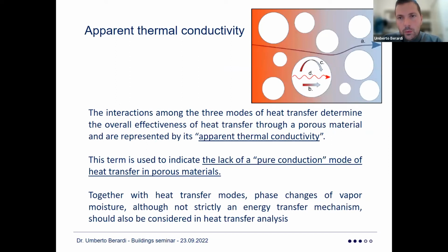And the reality is that what we use to have a low thermal conductivity, thanks to the possibility to cut as much as possible convection and conduction in the porosity of the foam, starts being much more significant because here you start getting water vapor instead of the blowing agent. So what we've been working on is the apparent thermal conductivity of these materials, and also the long-term apparent thermal conductivity.